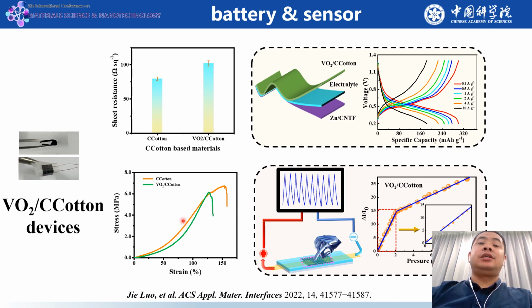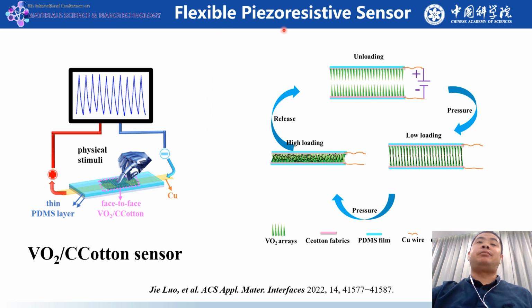In addition to the battery materials, vanadium dioxide carbonized cotton also can be used as sensing materials due to its brilliant mechanical property and the dielectric feature. Thus, we stuck two pieces of vanadium dioxide cotton face-to-face to prepare a sensor device. For this flexible piezoresistive sensor, the working mechanism is very simple. After loading a low pressure on the surface, the long aspect ratio vanadium dioxide rods will touch each other, and at the same time, rich channels will be built as the loading increases. Once the loading is released, the connection between the vanadium dioxide will be separated, and then the sensor will go back to the original state.